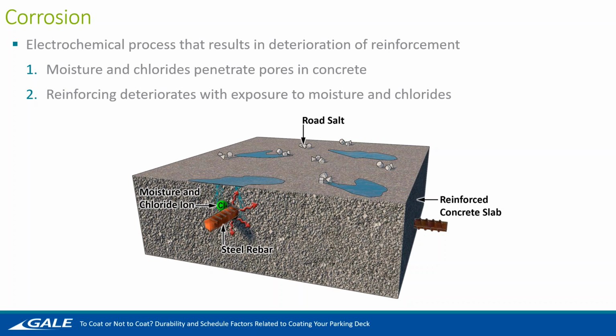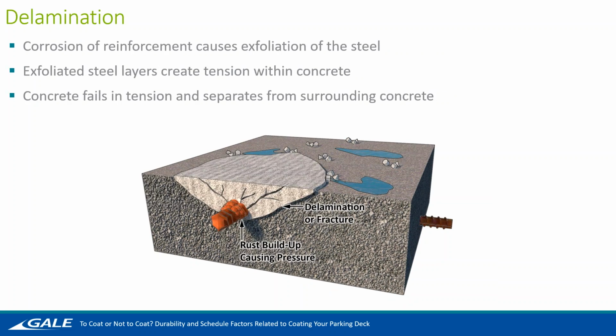So corrosion begins when the chloride ions make their way through the concrete and attach onto that rebar. So as the rebar begins to corrode and exfoliate, the steel will begin to push outward on the concrete. Concrete is meant to be used in compression. It's not strong in tension.